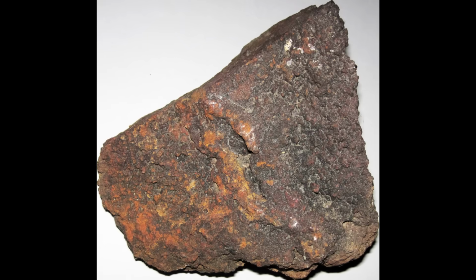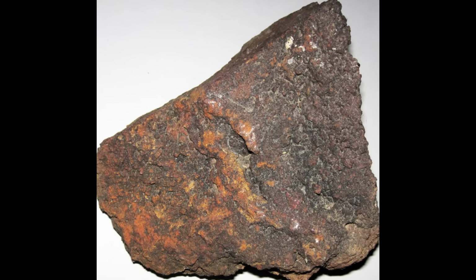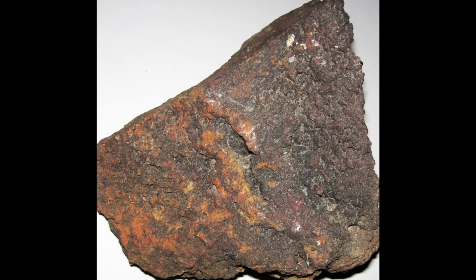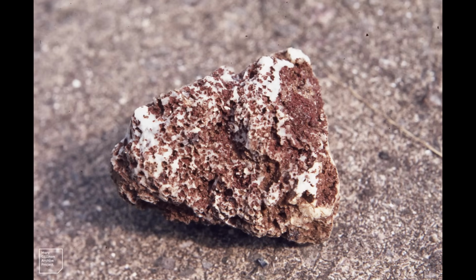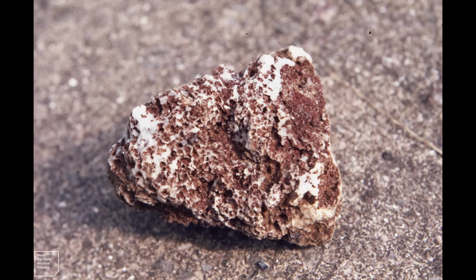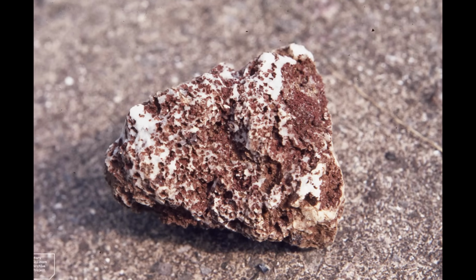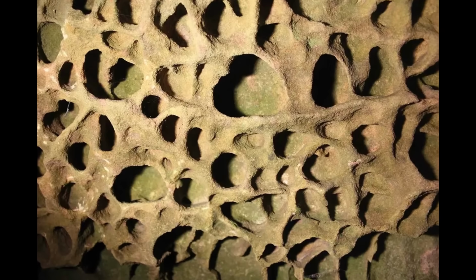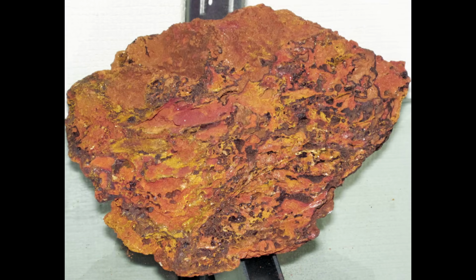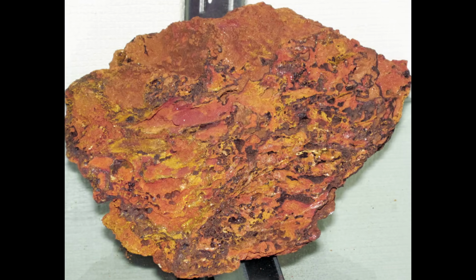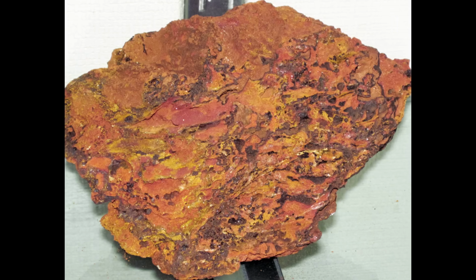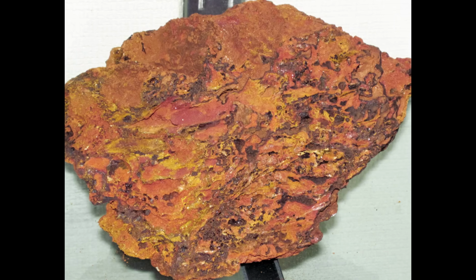True sulfide-derived iron, what prospectors call a gossan, often has a distinctive look. You might see boxwork textures, where cubic or irregular voids remain after pyrite crystals have completely dissolved out. You might notice a honeycomb-like structure, or sharp-edged cavities that don't match normal weathering patterns. These are negative spaces where sulfide crystals once existed. That's your first clue.